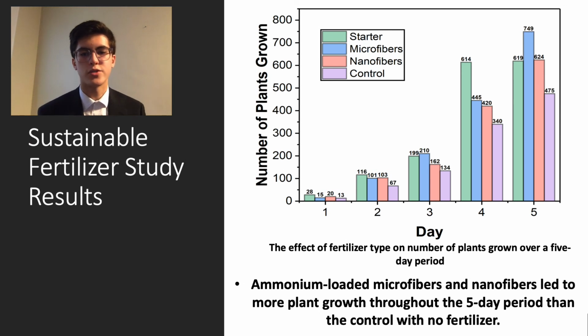In the fertilizer study, it can be noted that the ammonium-loaded microfibers and nanofibers promoted more plant growth throughout the 5-day period than the control with no fertilizer, suggesting that my materials can serve as successful, sustainable fertilizers. Overall, the ammonium-loaded microfibers promoted more plant growth than the ammonium-loaded nanofibers, possibly due to the superior hydrophilicity of the microfibers as determined by contact angle. Again, because of those larger pores, when you water the plants, the water will release more nitrogen, allowing for more potential plant growth.